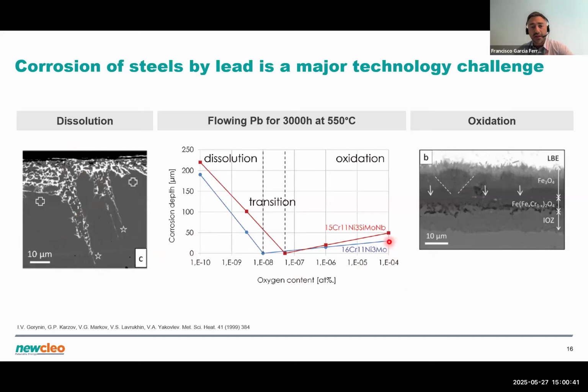And you can see in this kind of chart that the corrosion depth after the same amount of time at the same temperature is much lower. So despite the fact that oxidation is a form of corrosion, it's more controllable in principle than dissolution, and it leads to lower corrosion rates. So the state of the art relies on the utilization of oxygen injected into the system to achieve lower corrosion